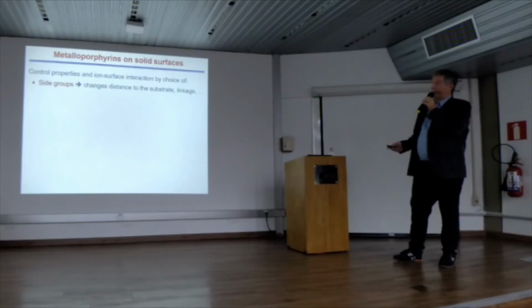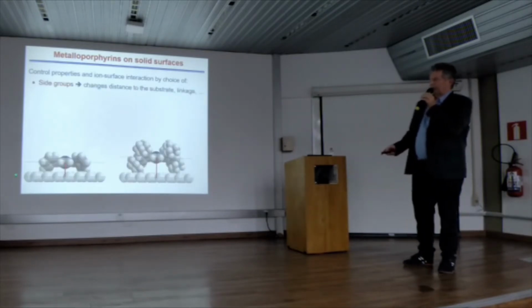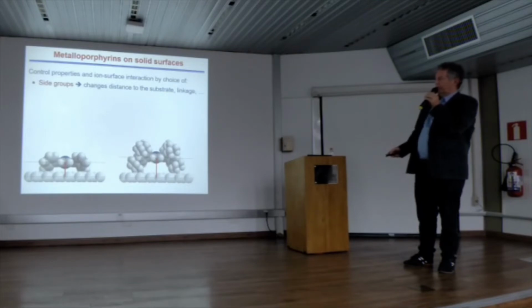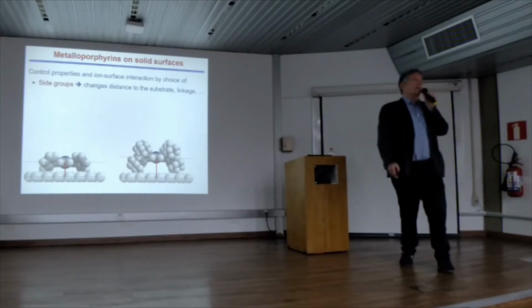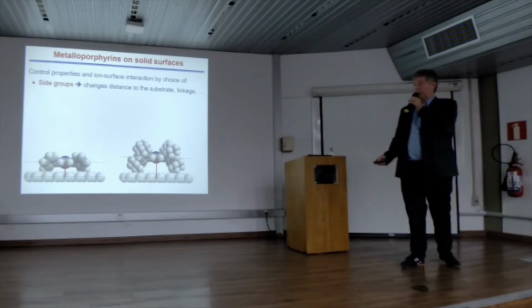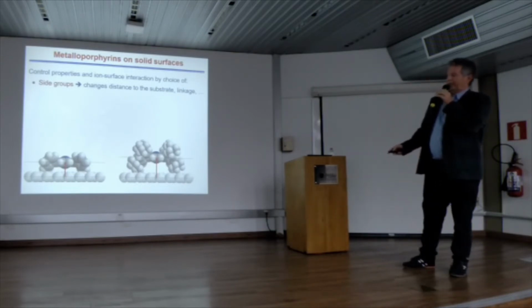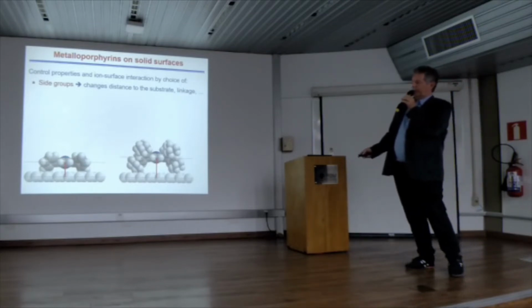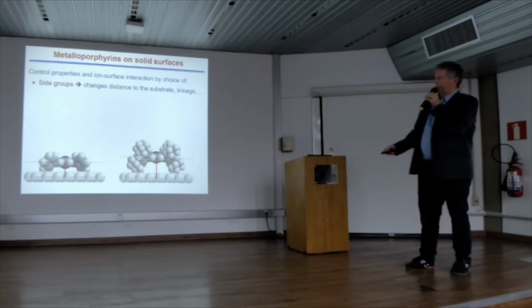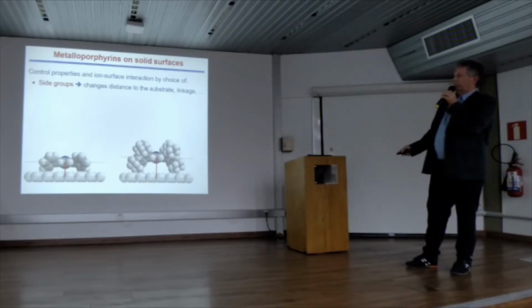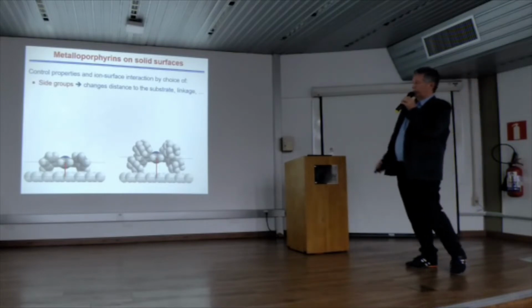We can vary the side groups. So down here, an example, here's a surface, a single crystal surface. We always use single crystal surfaces to have very well-defined systems. And then you have a porphyrin, a tetraphenylporphyrin, so phenyl groups here, and the molecule has a certain distance to the surface. You can measure that, for instance, with standing wave techniques. And then the metal atom has this distance. If you have more bulky groups, then this distance is increased. And of course, the electronic interaction between this here and this here is modified.